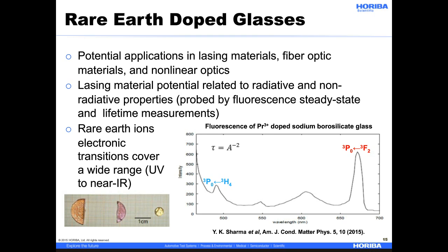The potential of a lasing material is related to the radiative and non-radiative properties of the material under study, which can be probed using both steady-state and time-resolved photoluminescence. In the example shown here, a steady-state PL spectrum is shown for a sample of praseodymium-doped sodium borosilicate glass. Two transitions at 490 nanometers and 672 nanometers were identified as being possible lasing transitions based on the calculated laser parameters, namely the spontaneous emission probability, branching ratio, radiative lifetime, and stimulated emission cross-section.